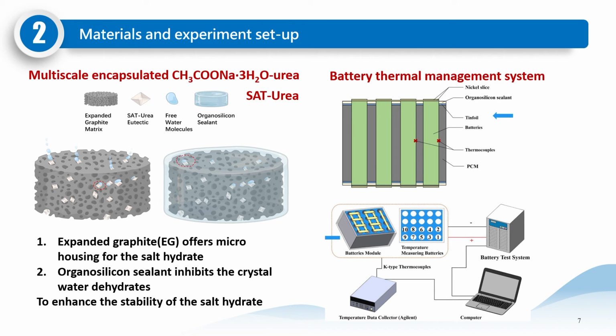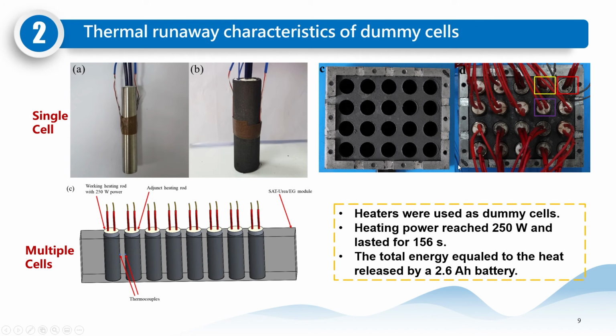as a macro encapsulation strategy. With this two-scale encapsulation strategy, we can enhance the stability of the salt hydrate, and this salt hydrate composite is then applied to a battery thermal management system. After that, we also tested the protection effects for the battery when it comes into the problems of thermal runaways.